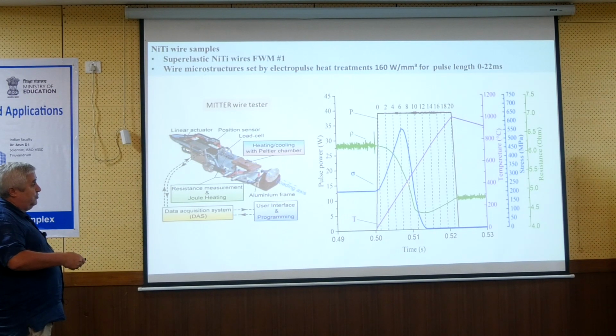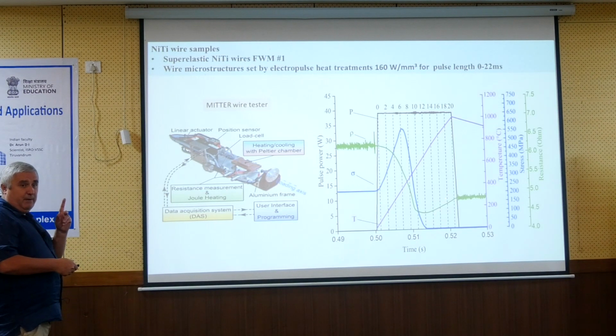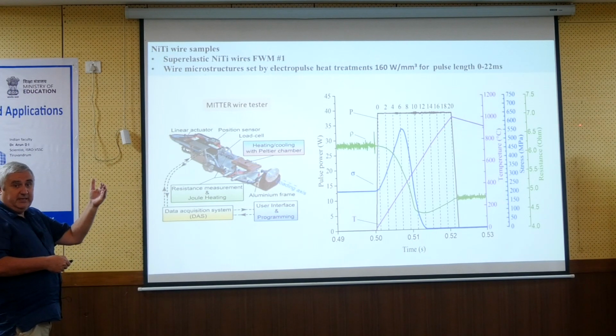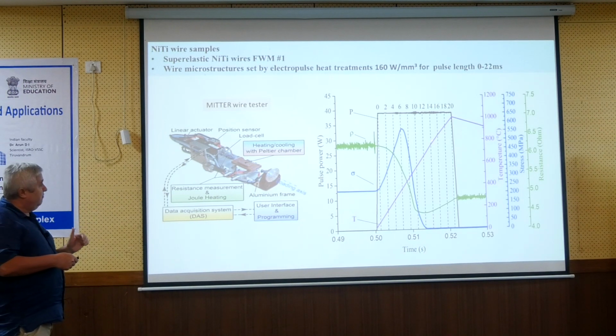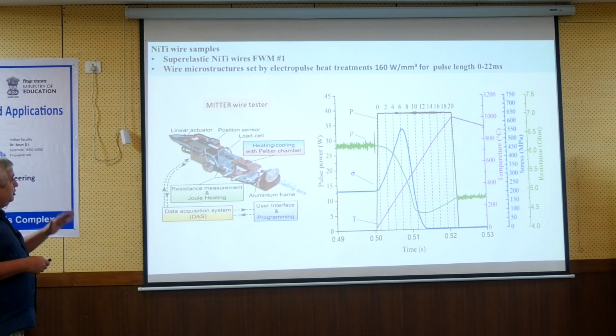And the fact that the martensite is transformed to austenite is evidenced by the decrease of the resistance. You know? Because the martensite has high resistance, austenite has lower resistance. Although you are heating the wire, and normally the resistance of metal will increase with increasing temperature, this occurs also, but the change due to the transformation from martensite to austenite is higher. Yeah?